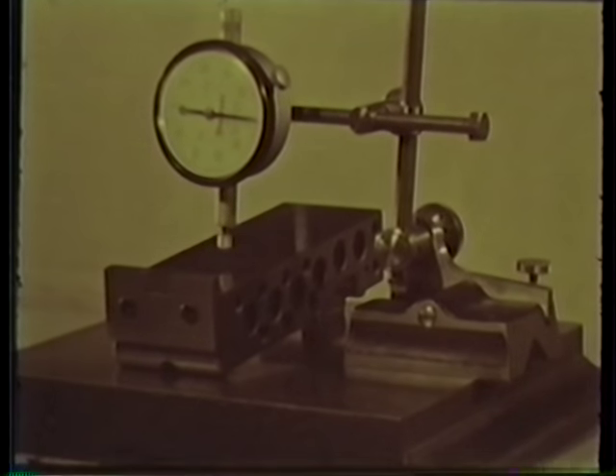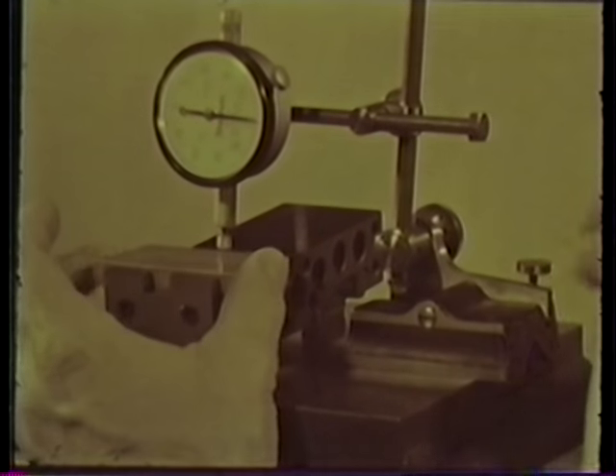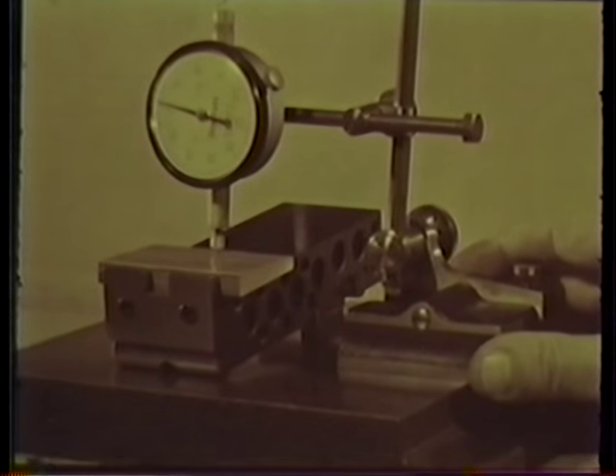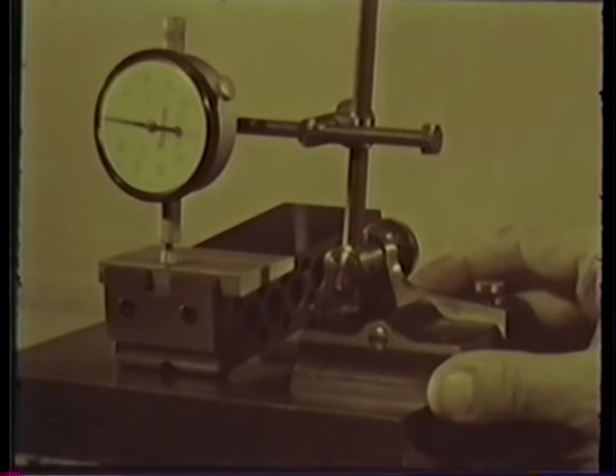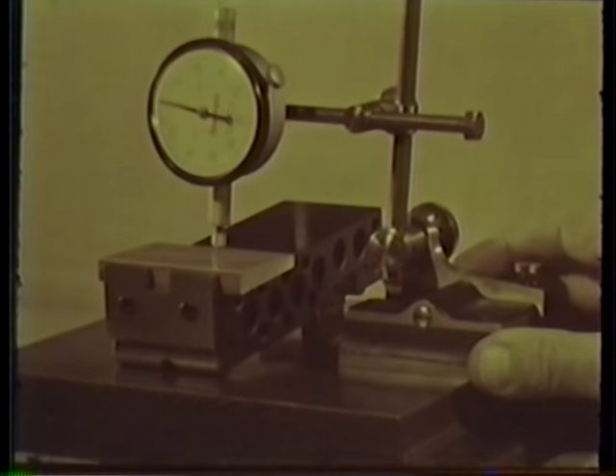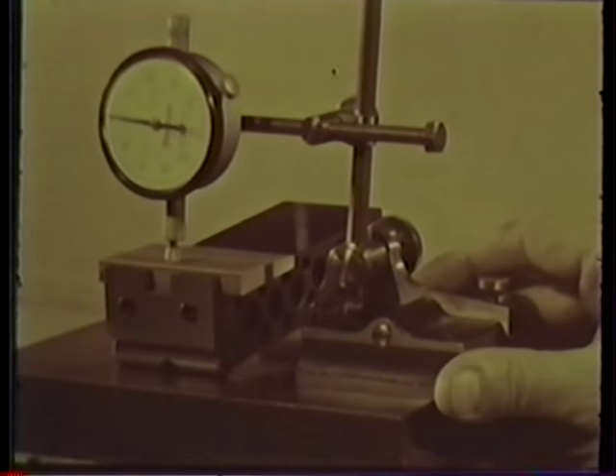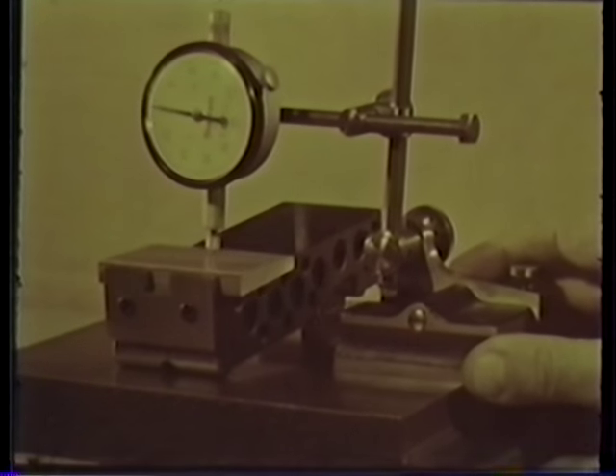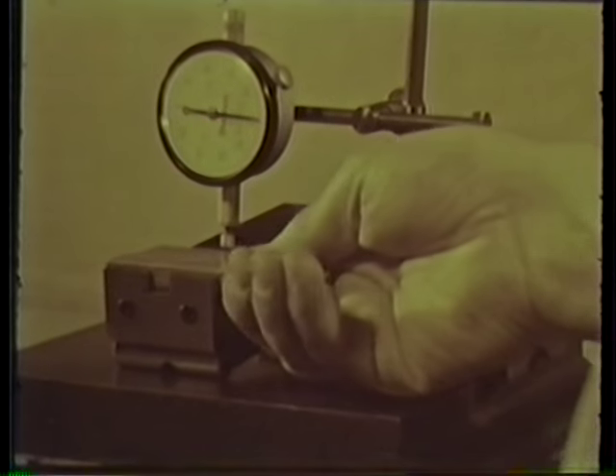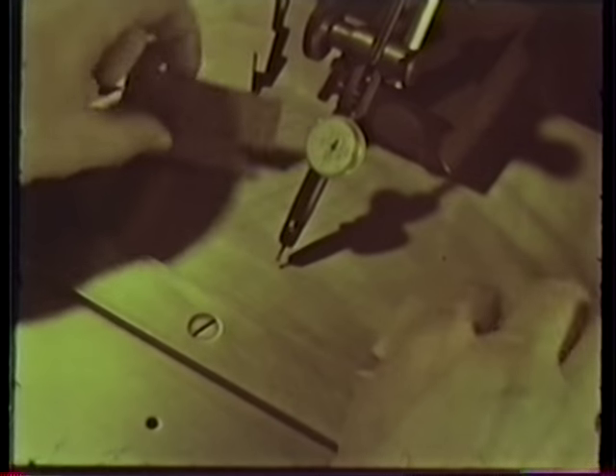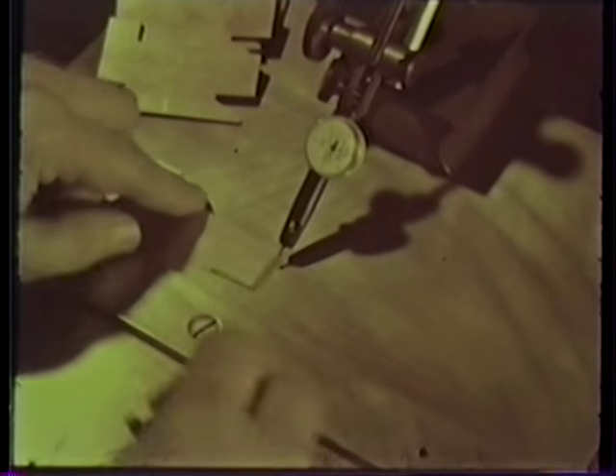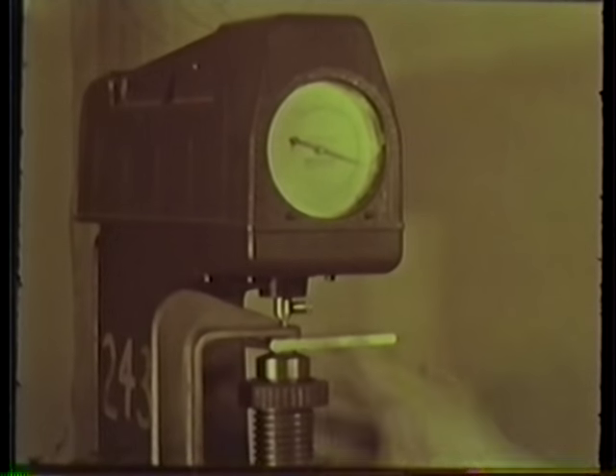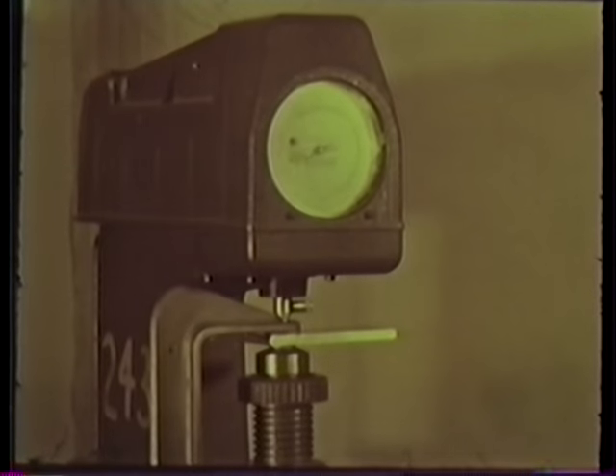While quality has been spot-checked at every operation, the copper gets a real fine tooth going over at this point. A sine bar is used to determine the angle of the wedge, the flatness and concavity, all essential to a tight commutator. The surfaces must be flat to within 0.02 of an inch per inch, and samples are cut off and sent to the laboratory to see if hardness and tensile strength are within tolerances.